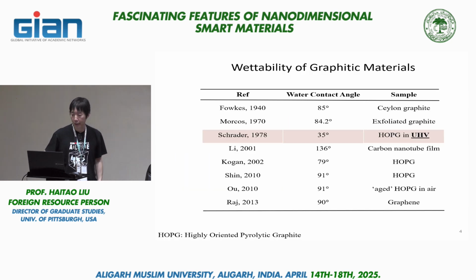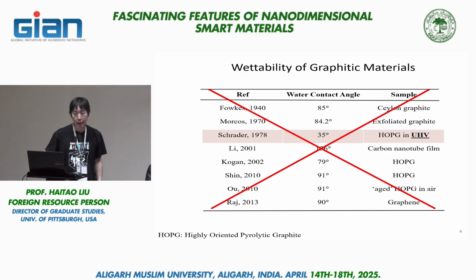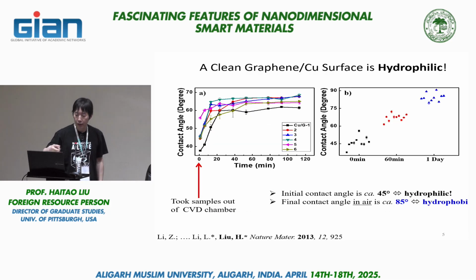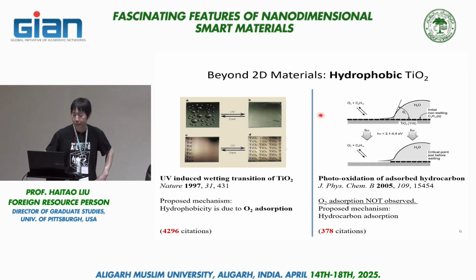So in case you missed my lecture yesterday, the basic thesis here is that the wettability measured in the literature on graphitic surfaces, which usually produces a hydrophobic behavior, is actually incorrect. And the reality is atmospheric hydrocarbon absorbs onto the surface, and that produces this rapid increase in the hydrophobicity of the surface. The origin of that is the atmospheric hydrocarbon absorption.